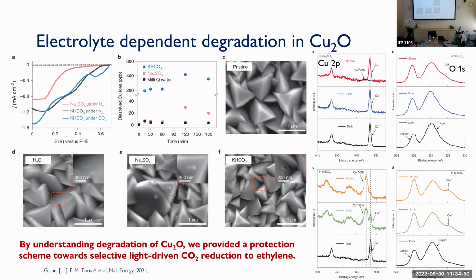The microenvironment is also important from the electrolyte perspective. This is now a different material. It's a material that I worked a lot on in the past 5 years, cuprous oxide. Very earth abundant material, but unfortunately also very unstable. It's reported for hydrogen production. My group for the first time reported cuprous oxide for CO2 reduction. So we studied the stability of this material in different environments and found out with operando X-ray photoelectron spectroscopy that the material transforms in different ways with respect to the electrolyte it is in. So it's extremely interesting because you don't change anything about the pH or the applied potential, but you just change the cations and the anions that you have in your solution.